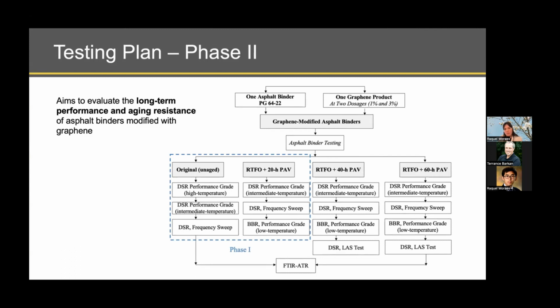The materials are very blendable. We had no issues with preparing the modified asphalt binders. We did not need specific equipment or higher temperature or adjustments in our routine protocol to modify the binder with the graphene additives. So overall, the phase 1 objectives were very positive for us. But again, it was a basic evaluation of these additives' effect in base binder for us to start to acquire knowledge of how these materials behave.